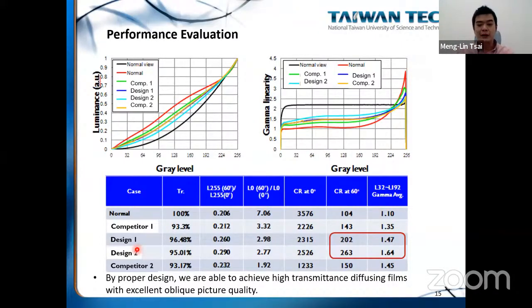We try to measure the contrast ratio. You can see that for a normal display, the contrast ratio at 60 degrees is like 100. After we apply an optical film, the contrast ratio at 60 degrees can be improved by like 2 times. And the transmittance loss is only like 3 to 5%, and this is acceptable.